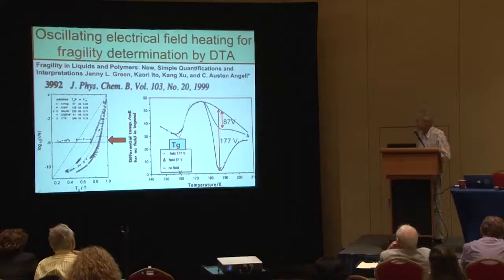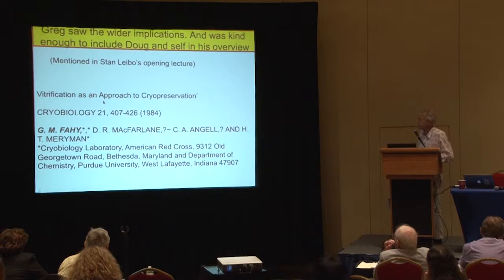And then you would have to tune your frequency as you heat up so that you're dissipating the energy at a maximum rate, always in tune with the relaxation time. You'd have to have a very clever apparatus to do this. But then you could really maximize the heating rate all the way from the bottom up to the top, where it's now thermodynamically stable again. That's a little bit complicated, and I'm sorry if I've expressed it badly, but at least it brings out the idea and the complications that you have facing you as you try to figure out good ways of avoiding the crystallization on the way back.